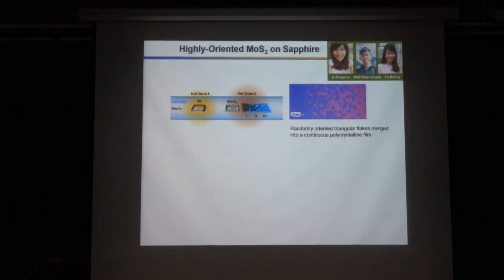Okay. The first one, we try to grow on sapphire substrate. So typically, this is simple. You just put some precursor like moly oxide and sulfur powder, and heat up. So you heat up, then the vapor will deposit on the substrate. So typically, we use the sapphire substrate, and the blue one is the TMD material, like MoS2. So you can see some triangular grains randomly oriented on the substrate.